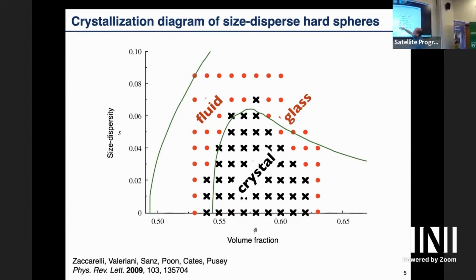That's well known. Then if you add dispersity with this Gaussian distribution, you see it gets harder to form crystals. Here the density goes up, and then at one point it also goes down again. So there's this bump here. They're all FCC crystal. So very simple periodic packing, the packing you know from packing oranges in the supermarket. So we have a glass fluid, and that has been known for a long time. This is one exemplary work where this was taken from. You see there's nothing special happening, except that roughly at 5 to 6% dispersity it becomes impossible to find crystals.